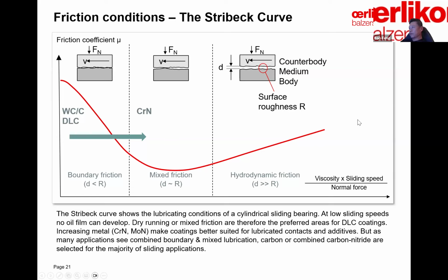And keep moving to the right, you get into the elastohydrodynamic lubrication regime, where you have full oil film separation between the surfaces. At that point, you no longer harvest the benefit of the coatings. This is a typical contact condition for automotive applications, where you have low contact pressure but high speed. But also keep in mind that you also have frequent start and stop conditions, where you throw the contact lubrication conditions back and forth between boundary lubrication and hydrodynamic lubrication. In other words, you still need the coating protection for the components.